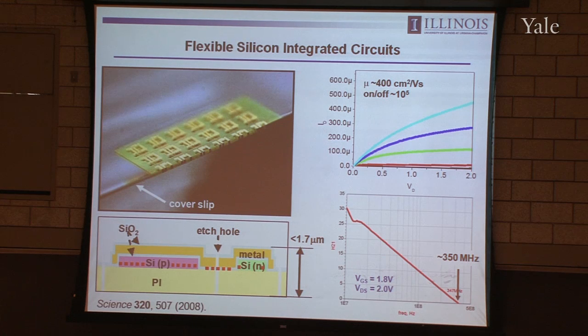This is a silicon CMOS integrated circuit, where the silicon layers, in this case, are sitting on top of a polymer sheet, where we select the polymer sheet to be very thin, but not arbitrarily thin, because we design the system so that the neutral mechanical plane is coincident with the most brittle layer in these circuits, which happens to be the silicon. The neutral mechanical plane is also a simple concept in mechanics. You have a sheet of material, and you bend it in this way, then the top surface is in tension, the bottom surface is in compression. For uniform material, the geometric midpoint sees zero bend-induced strain. And the neutral mechanical axis in this system is not the geometric midpoint, but you compute where it is.